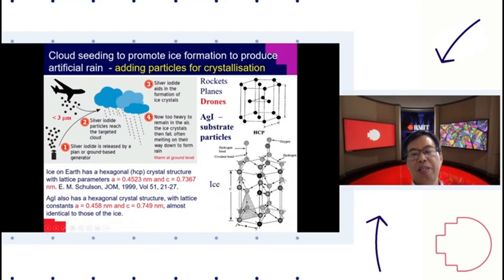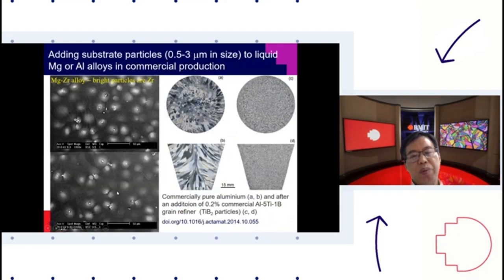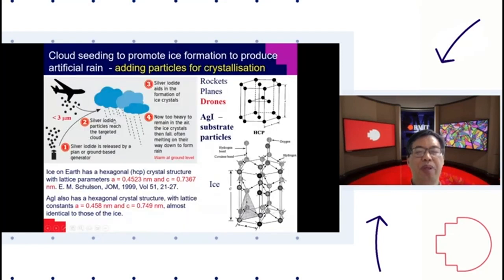The silver iodide and the ice crystal have a similar crystal structure and similar lattice parameters, so they are almost identical. We do this in the commercial production of aluminum alloys and magnesium alloys. For example, these bright particles are zirconium particles. In the commercial production of a large group of magnesium alloys, we add this small zirconium particle, and many other particles similar to this.